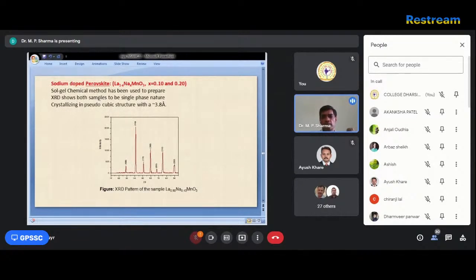Another one is sodium doped perovskites. Okay, so now this is the sodium one. It is given by ABO3 type structure. In the sodium doped perovskites, the aim is to support the findings based on the study of divalent cation substitution at LaMnO3. When you go to long range FM order, or an insulator metal transition, the system shows it with more than 1/3 atomic fraction. It means up to 1/3 there is some disordering, but after this it shows an ordered state.